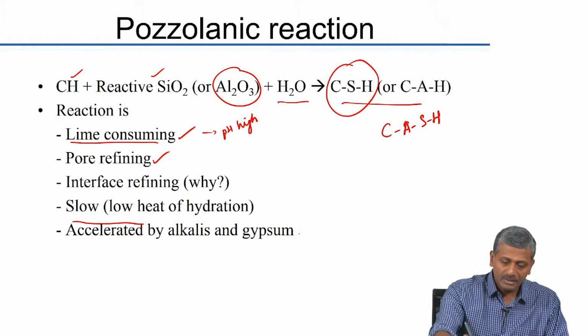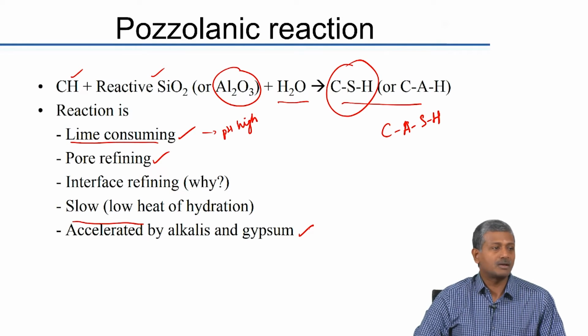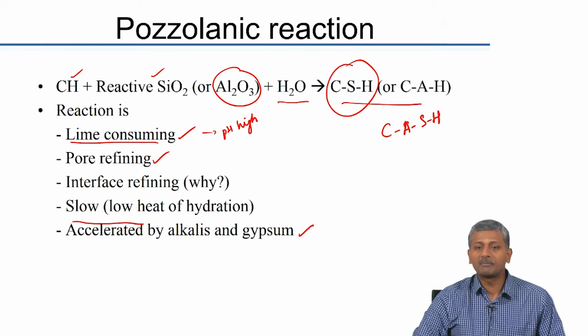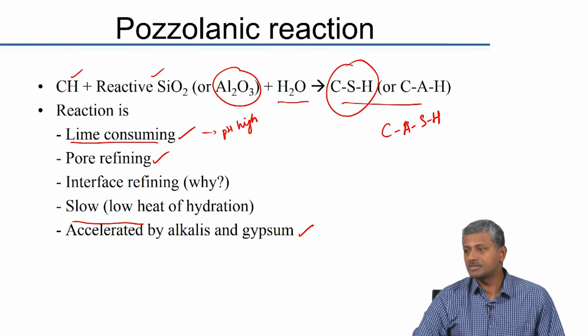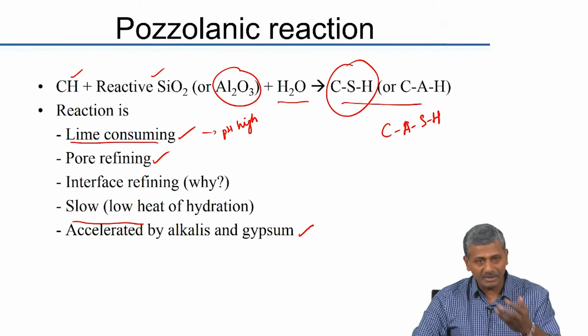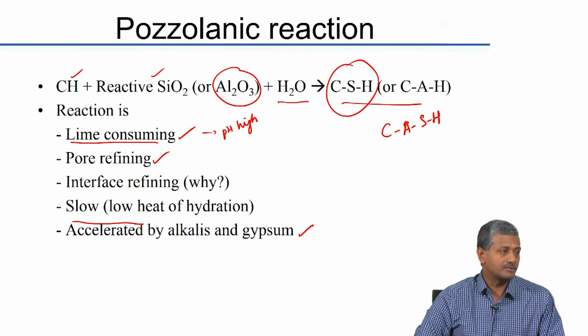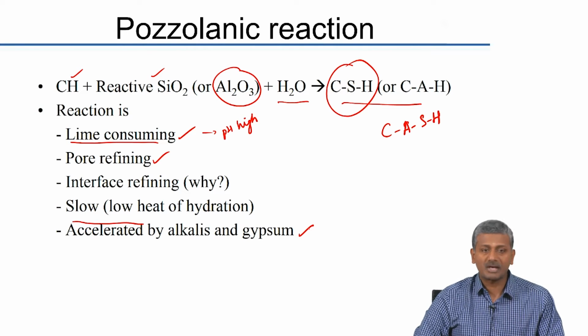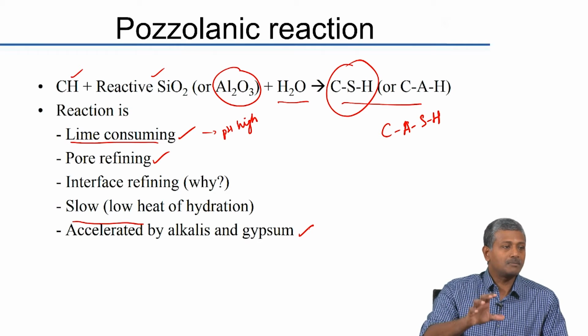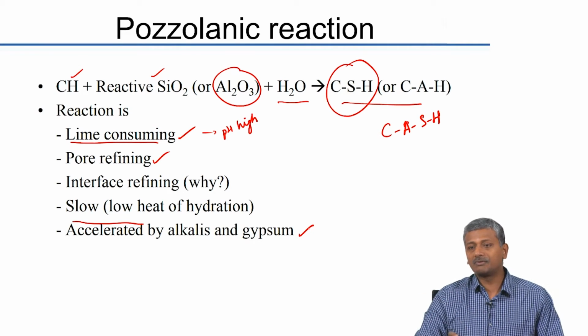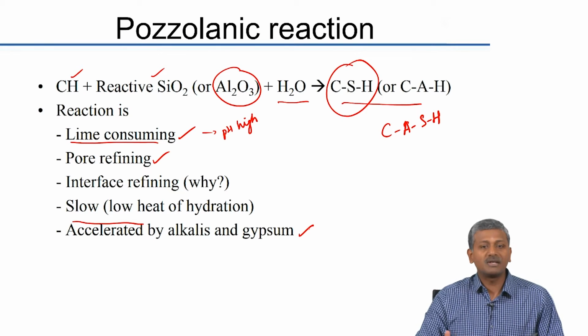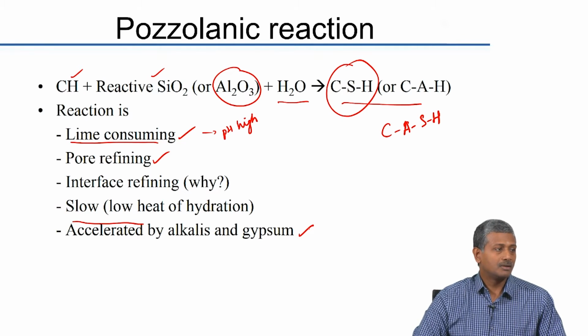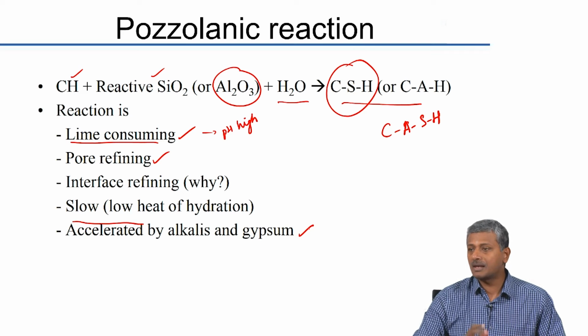And this reaction is generally accelerated in the presence of alkalis and gypsum. Where are the alkalis and gypsum coming from? From the cement clinker, right. Cement is contributing the gypsum and the alkalis. Okay. So, in the presence of alkalis and gypsum, this reaction is much faster than it would be otherwise. So, if you take a pure system of lime, that is calcium hydroxide, and react with fly ash in the presence of moisture, your system will take a long time to attain strength. Okay. But in the presence of cement, because the alkalis and gypsum are getting contributed by the cement, you actually can attain strength much faster even with fly ash based systems.